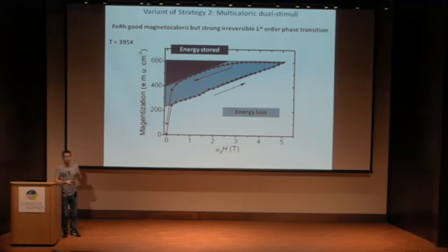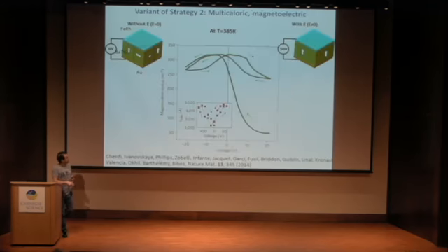So you can look for second-order phase transitions, and then you can avoid it. Or you can use this system and do the following. Iron rhodium on top of barium titanate, which is the ferroelectric part. We showed 2 years ago that there is a very nice magnetoelectric coupling at the interface between this ferroelectric and this ferromagnetic system.